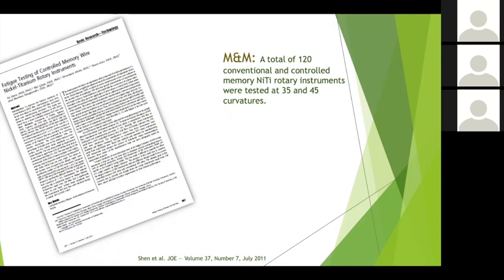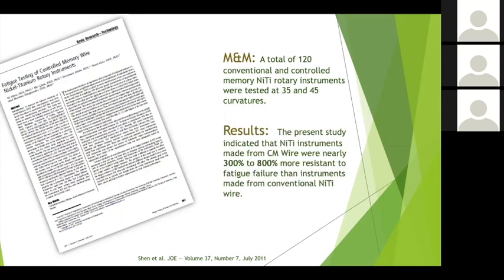So she takes 120 of these conventional controlled memory files and regular conventional files. And she tests them at curvatures of 35 and 45. And she finds that the nickel titanium instruments that are made from controlled memory are between 300 to 800% more resistant to fatigue failure than instruments made from the conventional NiTi wire generations 1 through 3.